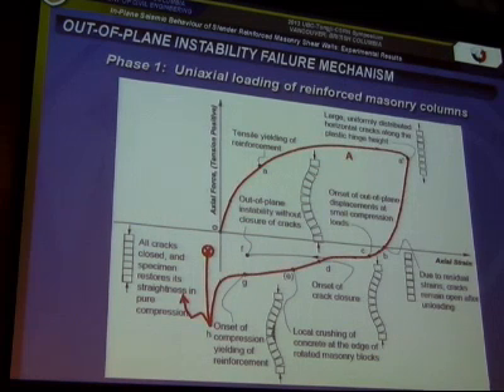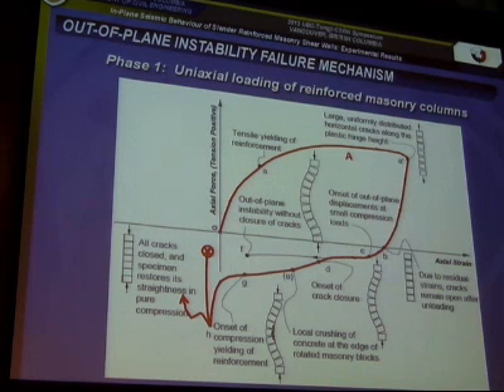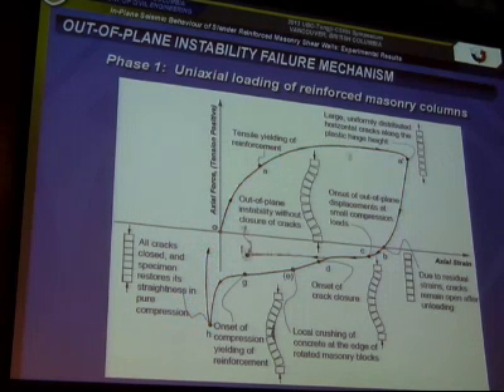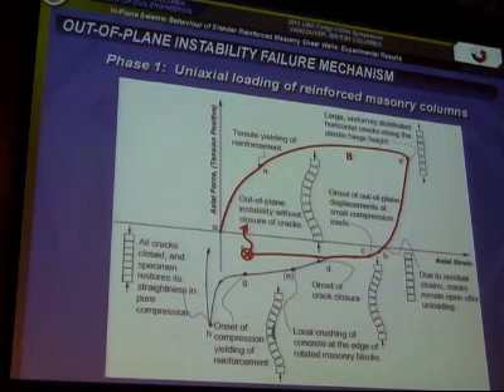The first path would be if this face shell contact occurred before a critical limit, which was found to be half the wall thickness, and that face shell contact would cause a stabilizing moment over the cross-section, which would act to decrease the out-of-plane displacement. If, however, this contact did not occur before this critical out-of-plane displacement, the displacements would continue in an unstable manner until failure would occur.